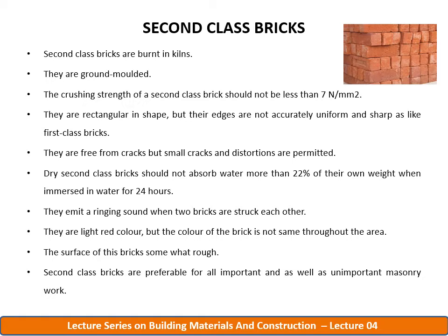When second class bricks are immersed in water for 24 hours, the water absorption capacity should not be more than 22% of its own weight. They emit a clear sound when two bricks are struck against each other.